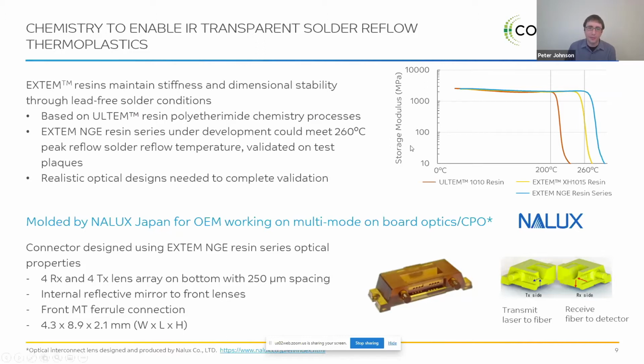And how we were looking at this was storage modulus is sort of a reference of how stiff something is. So if you're trying to, say, bend a part, how stiff was it to that bending motion? When we get up to about 200 degrees C, ULTEM will start having some softness and it will start actually deforming. With these EXTEM materials, we can push it up to and beyond 260 degrees C for the peak reflow temperature that we know occurs in lead-free soldering.